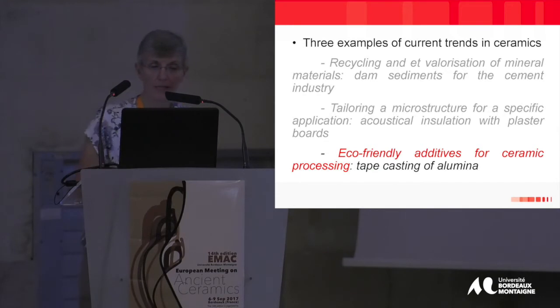Last example is the use of eco-friendly additive for ceramic processing, and I give you the example of the tape casting of alumina. So what is tape casting? Basically, we mix a ceramic powder with additives: a binder, plasticizer, dispersant, to obtain a ceramic suspension, which is cast onto a substrate.